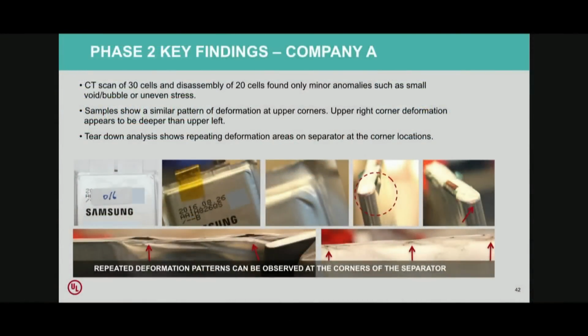We found minor anomalies such as small void, bubbles, or uneven stress. The samples also show a similar pattern of deformation on the upper corners. The upper right corner deformation appears to be deeper than those on the upper left. And finally, a teardown analysis shows repeated deformation areas on separator at the corner locations.